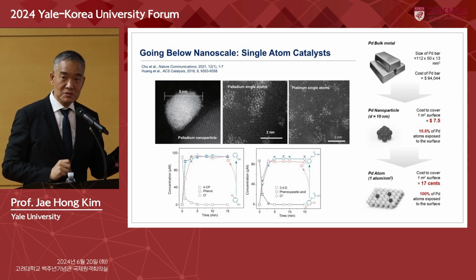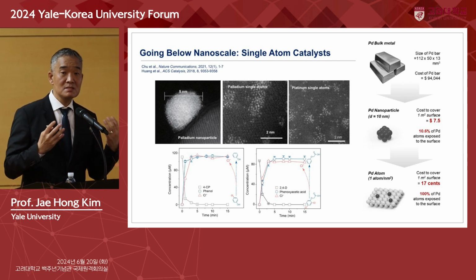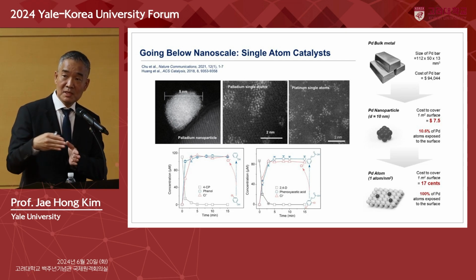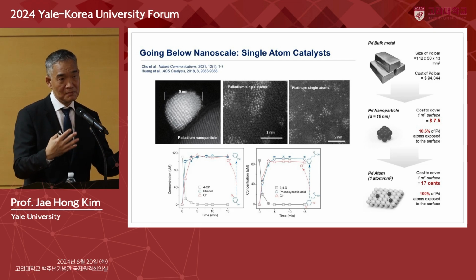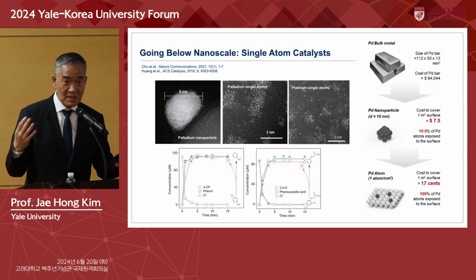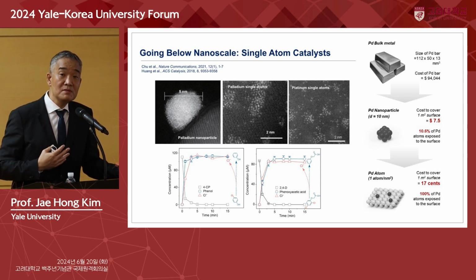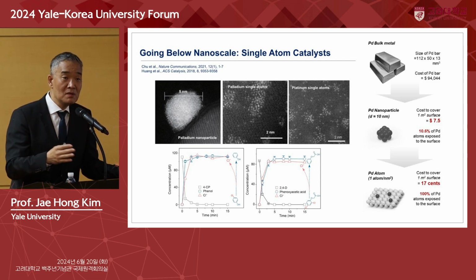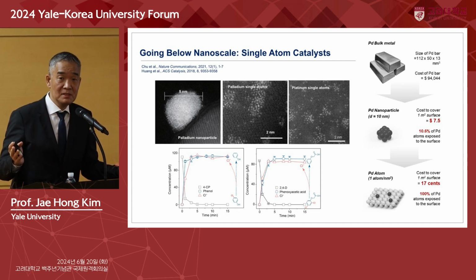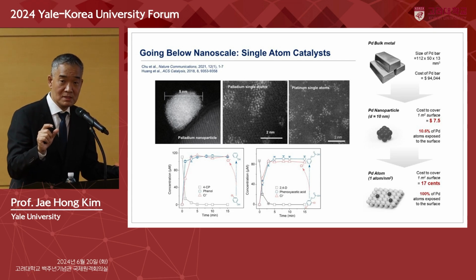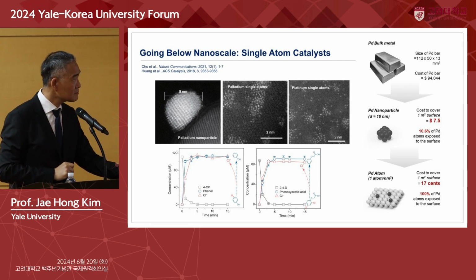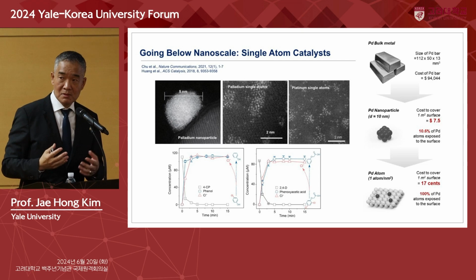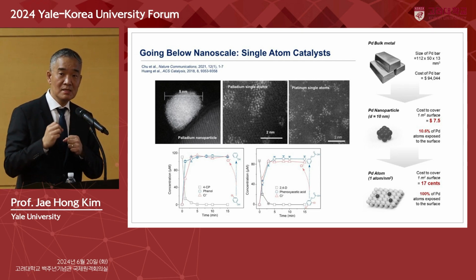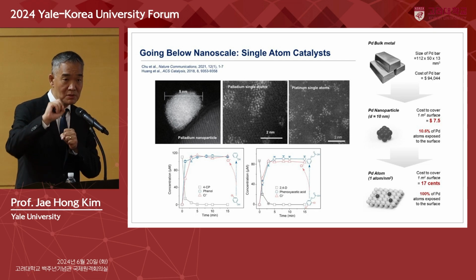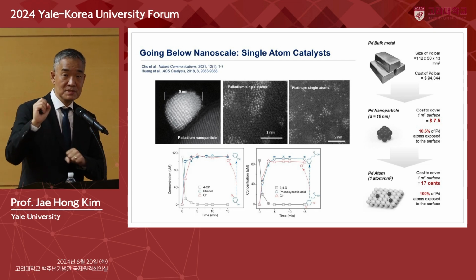So we've been studying the dehalogenation reaction, but if you do it on a nanoparticle, this reductive power goes not only onto breaking the carbon-chlorine bond, but also reduces the double bonds in the other parts of the molecule. And that is a problem because when you're talking about treating water, your water has millions of different stuff, okay? And what you want to do is use your redox power just to break what you don't want, such as the carbon-halogen bond, okay? So we found that when palladium or platinum is in the single atom configuration, you use all their reduction power to dehalogenate with near 100% selectivity.